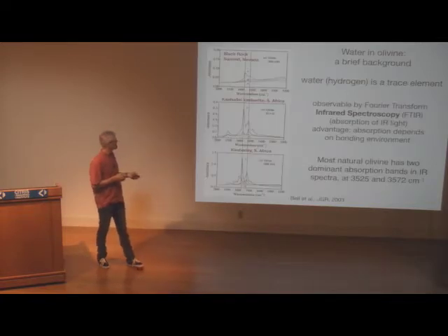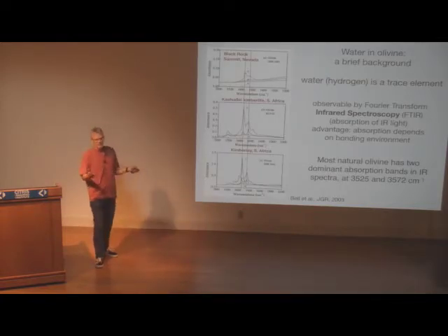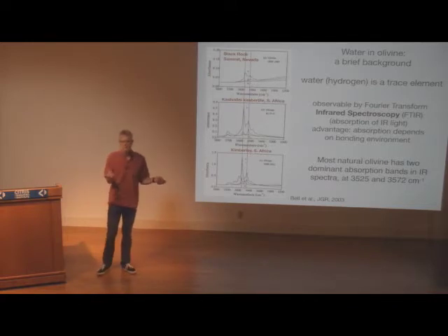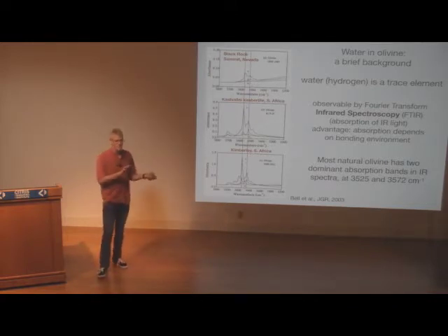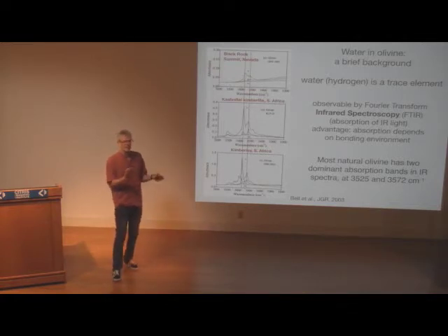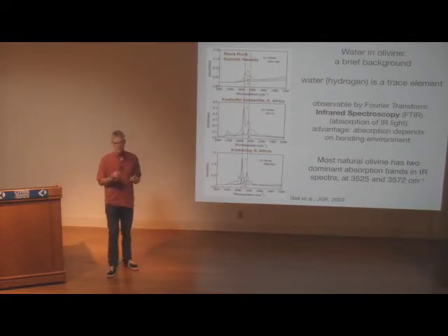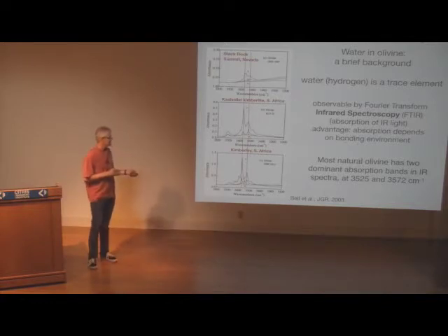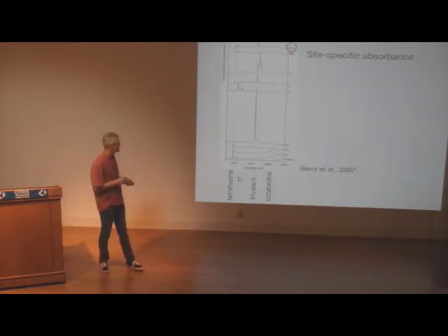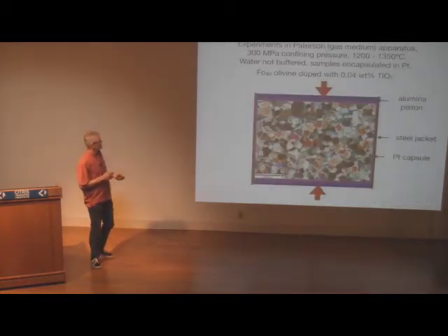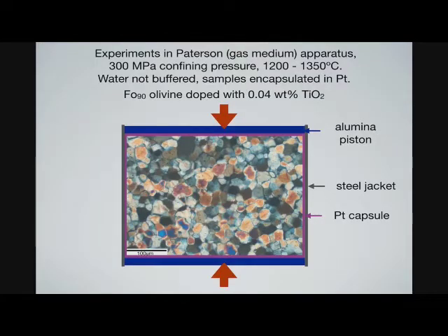And if you look through, so this is natural olivines. If you look at the concentration of titanium, go through some thermodynamics and so on, and calculate defect concentrations, the order of magnitude of the extrinsic defects, such as titanium, calcium, and so on, is very similar to the calculated concentration of intrinsic defects. Meaning that these extrinsic defects are probably very important for all properties of olivine. So we can confirm that with deformation experiments.